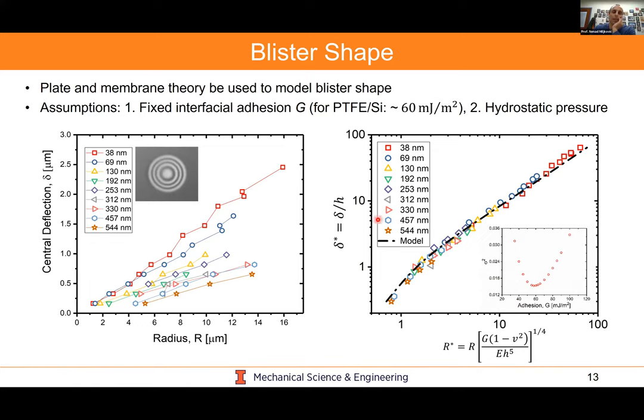It turns out that you could normalize this by the thickness of the film, which is H. So if you take delta over H and call it delta star, you could also form a mechanics-based non-dimensional radius. You could see that the majority of these collapse onto one particular curve. This non-dimensional radius is based on plate and membrane theory. G is the adhesion to the substrate. Nu here is the Poisson's ratio. E is the Young's modulus. And H is the thickness of the film that you're depositing.